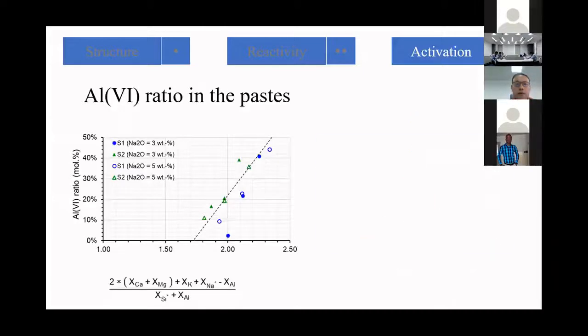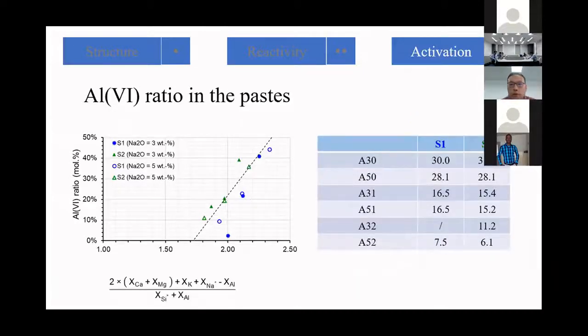And from this deconvolution, we could get a ratio of hydrotalcite in the hydrated paste. And from the result, we could see clearly that silicate concentration is determinative for the formation of the hydrotalcite. The formation of hydrotalcite depends solely, or nearly only, on the silicate concentration.